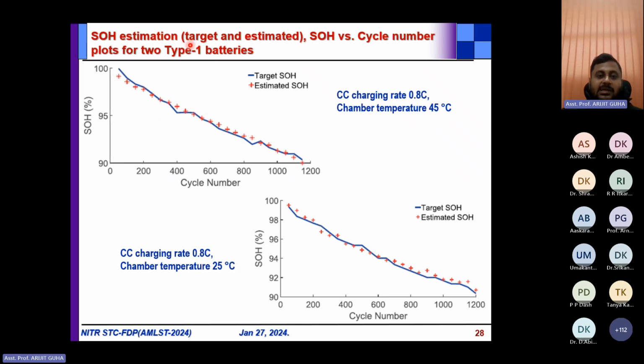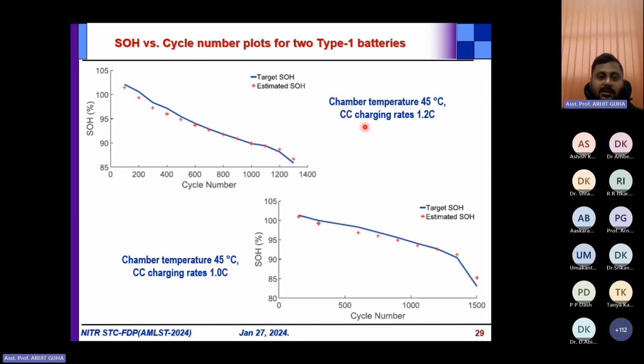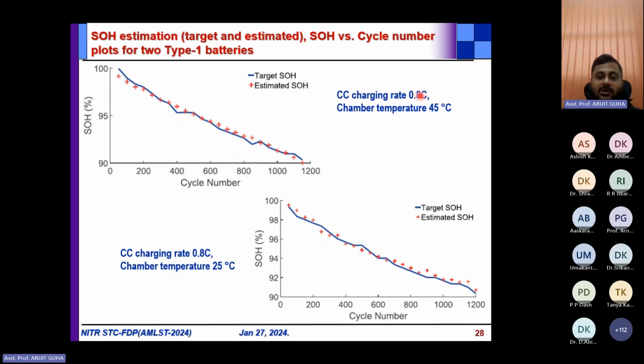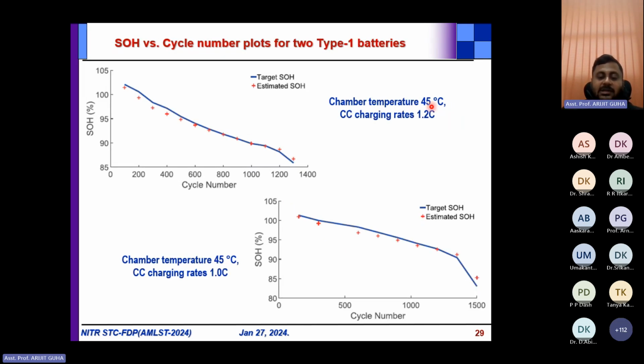This is based on the type 1 batteries, on which the artificial neural network has been trained. Now here you can see that the charging rate has been changed. In the previous case, the charging rate was kept constant and the chamber temperature was changed. Now in the second case, the chamber temperature was kept constant and the charging rate was changed. Here it is 1.2 C, here it is 1 C. That time also our proposed method is performing quite well. You can see here.